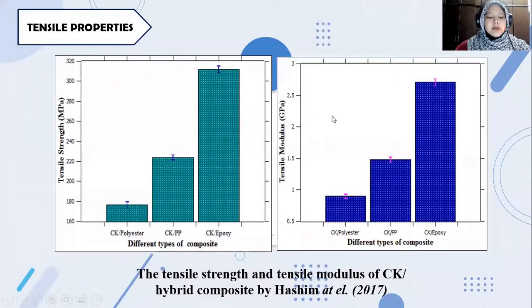Next, the bar chart of the tensile strength and tensile modulus of carbon Kevlar hybrid composite by Hashim et al. in 2017. CK epoxy has the highest tensile strength and tensile modulus. This may be because the addition of carbon contributes to good results and may give good agglomeration between the particles. This also proves that carbon can improve the hybrid composite of the materials.